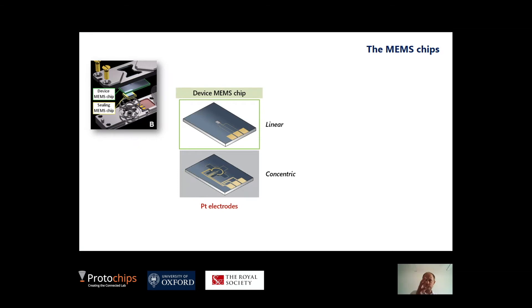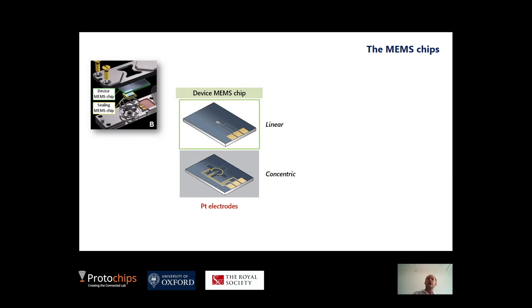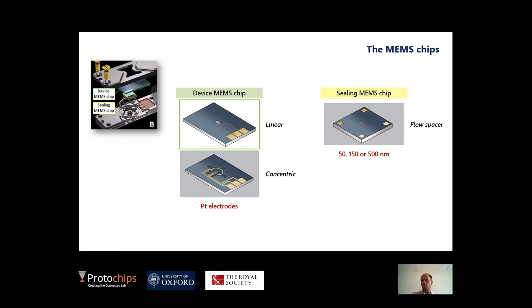Just a little bit of specifics on the MEMS chips. There's actually a variety of chips you can employ, because depending on the science you want to do you may have different requirements. For us, we're wanting to do electrochemical studies, so we do need some form of electrode geometry to supply a bias. In particular, we're wanting to understand the electrolyte chemistry and how it behaves just on a metal electrode — we're not interested in, say, interaction with graphite or some cathode metal oxide material, because we just wanted to see how it would interact with the current collector. We just wanted platinum electrodes — platinum working, and also counter and reference electrodes — because platinum shouldn't have any parasitic or confounding side reactions or alloying reactions. We can just look at how the calcium plates and strips off of this platinum electrode, and then we seal that sandwich up together with a sealing membrane with some flow spaces configured, allowing us to flow liquid across or to replenish the electrolyte across the active area.